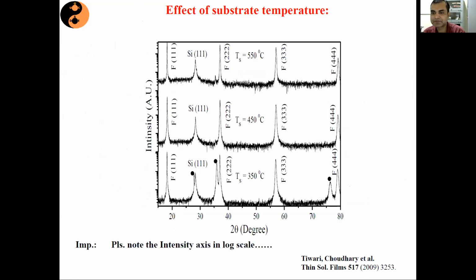Now, what is the role of substrate temperature? Fe3O4 is a very funny material. Fe3O4 is composed of FeO plus Fe2O3. So you can have the FeO phase, you can have the Fe2O3 phase, and you can have the Fe3O4 phase. How do we really check that? If you see that when the substrate temperature was lower, say 350 degrees centigrade, we get, besides the 111 peak, some additional peaks coming up. And those additional peaks are the FeO phase.